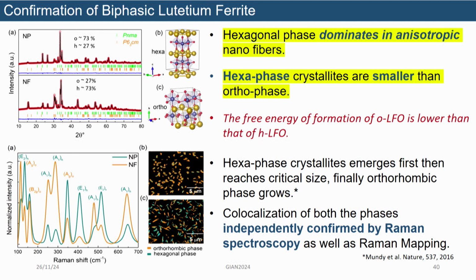So, we tried to understand, and we concluded that it is the strain associated with the synthesis of nanofiber that is contributing, and that is why it is favoring the hexagonal phase in the nanofibers. So, hexagonal is dominant in nanofiber. Now, we also investigated Raman, and we found that in both cases orthorhombic and hexagonal both exist.